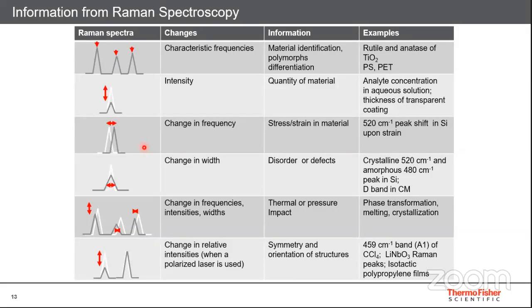Raman spectroscopy is very sensitive to changes in the physical properties of the molecule. For example, if there is stress and strain in the material, then you will see a shift or change in the frequency of the Raman shift. So for example, you see a shift of the 520 centimeter inverse peak in silicon when it undergoes strain. Similarly, there is a change in the width. You can see the Raman peak width increasing, which shows that there is a disorder or a defect present in your molecule. So, for example, crystalline silicon shows a peak at 520, while amorphous silicon absorbs at around 480 centimeter inverse.